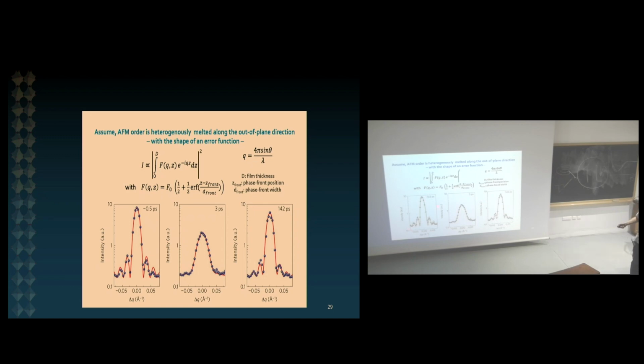So before the excitation pulse arrives, we have a scattering peak that has these finite size oscillations around it. That's reflecting a very well ordered, sharp interface. So a well-defined thin film carrying this antiferromagnetic order. But if you now measure the same peak 3 picoseconds after you have excited the material, not only have you lost a lot of intensity, so you are disordering the film, but you're also changing dramatically the width of this peak, which is becoming a blob. And then if you let time go by, the system gradually recovers its finite size fringes.